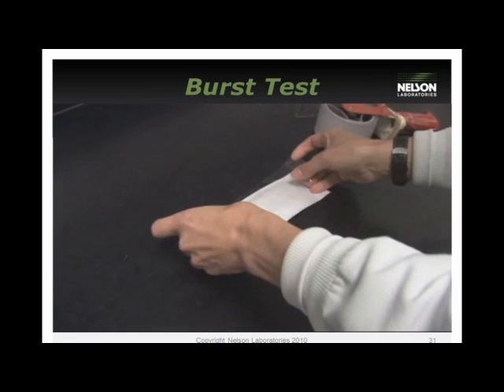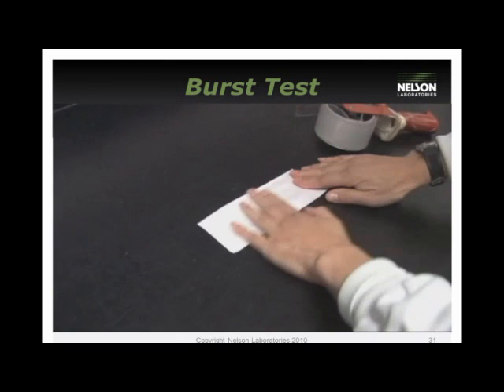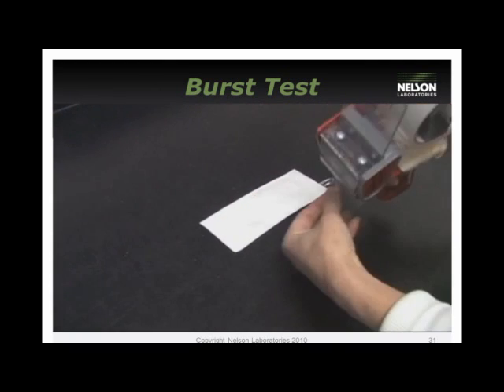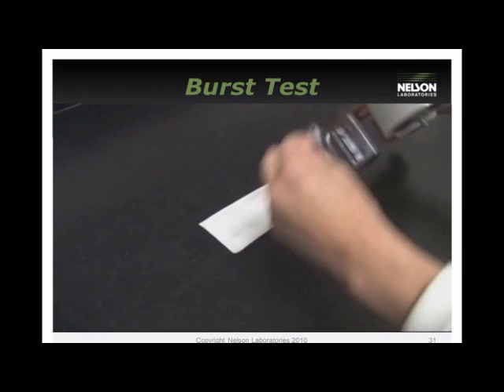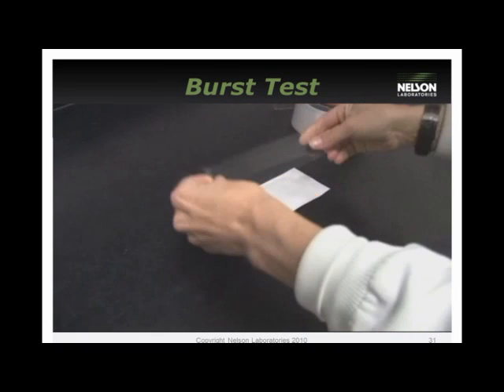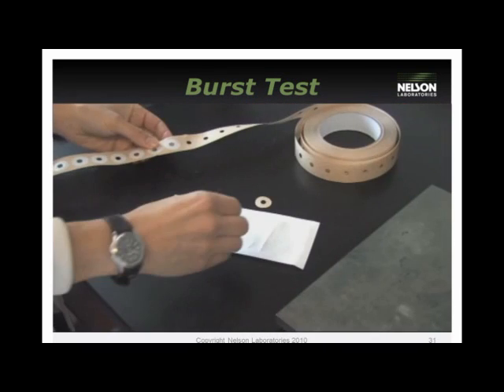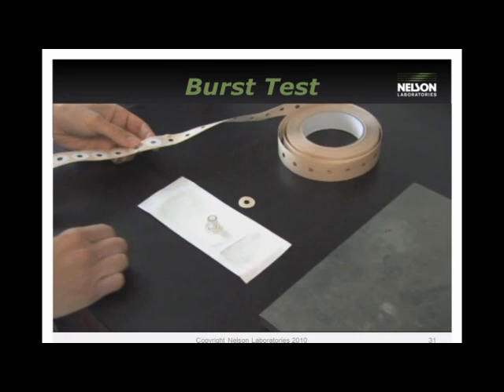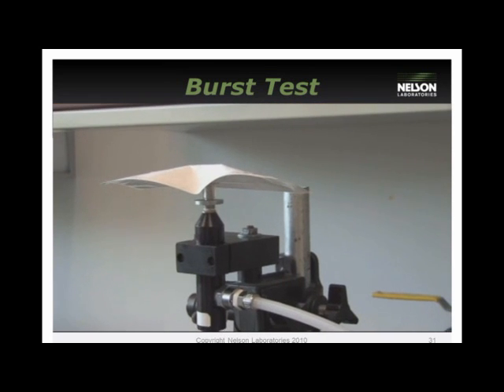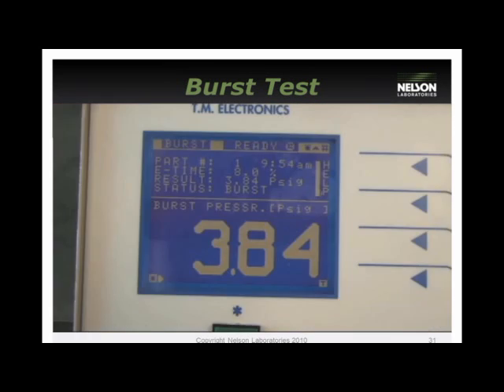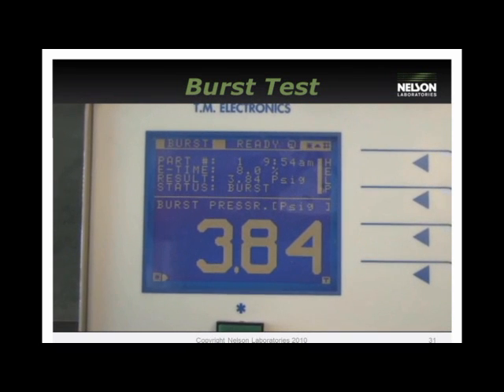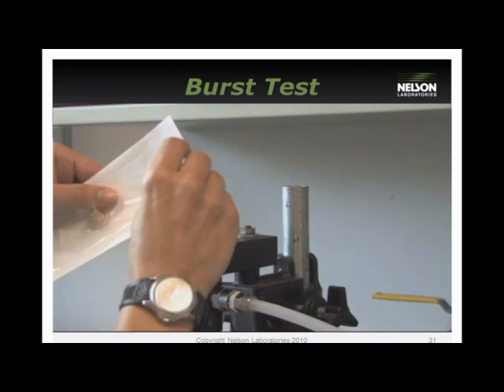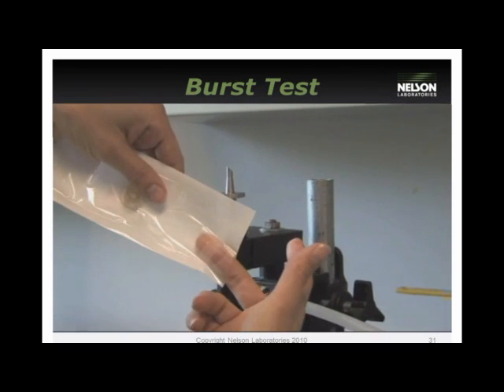Burst is a whole package strength test. Porous packages must be sealed with tape prior to testing to prevent air from escaping through the porous layer, allowing the package to properly pressurize. The package is attached to the tester with a port and inflated until it bursts. The maximum pressure is measured, and the technician records the burst location.